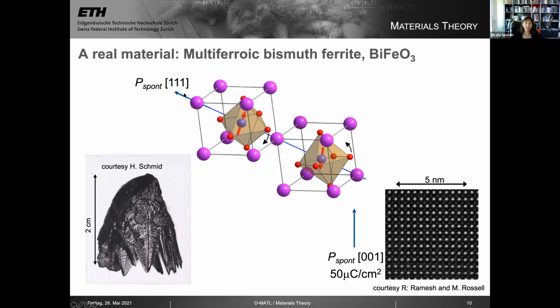Yeah, and so the polarization is along the 111 direction. This film is grown so that 111 would be in the diagonal. And so the polarization, this is a kind of a thin film, a layer, the polarization that's pointing out of the plane of the film, which is the part that can be measured, has a value of about 50 microcoulombs per square centimeter. And we'll come back to that number later. You don't have to remember it.